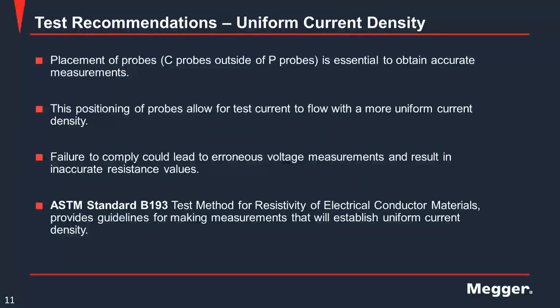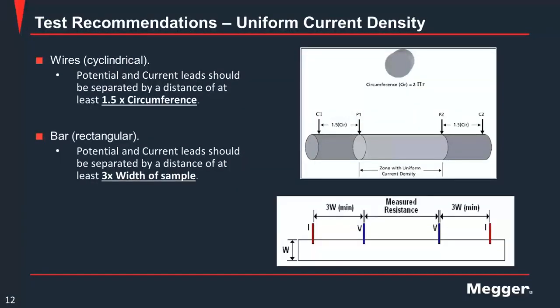So based on the ASTM standard B193, which gives you information about the guideline on how the measurement can be made to establish the uniform current density, this standard is very useful to understand how to place your probe and how to get the uniform current density when you want to do a low resistance measurement. This is some information that you will find in the ASTM standard, to define the uniform current density.